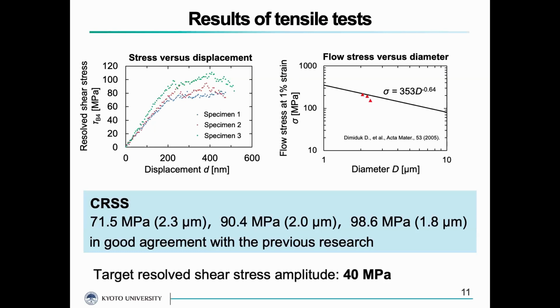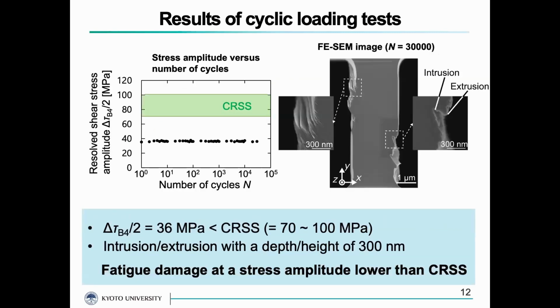And we determined the displacement amplitude in the cyclic loading test to satisfy a resolved shear stress amplitude of about 40 megapascal. That was about half of CRSS in monotonic loading. And then we conducted 30,000 cyclic loading tests. That was the maximum cyclic number in this study. The resolved shear stress amplitude was about 36 megapascal, clearly lower than CRSS.